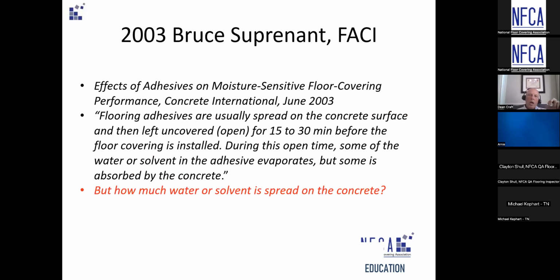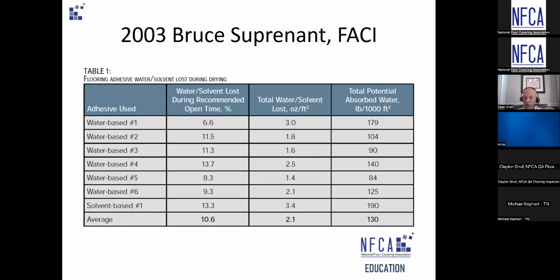And one of the things they showed is just how much water or solvent some of these adhesives imparted to the project. So you can see 6 water-based adhesives, separate adhesives, 1 solvent-based, and the average. And you see the open time. The one is a very short open time, number one, but the rest of them average 10.6. Then look at the middle column. What they did was they spread it down, noted the open time, and they weighed the sample very, very carefully. And at the end of the open time, they weighed it again.